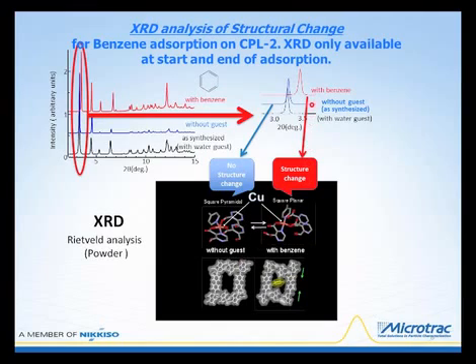But also, when we take a look closer at the MOF after exposure to benzene, there is a structural change that occurs according to the XRD analysis, where we're using a Rietveld analysis on the powder. And we undergo a structural change from the square pyramidal to a square planar, and the structure has changed as a result of the benzene molecule being adsorbed into the structure.